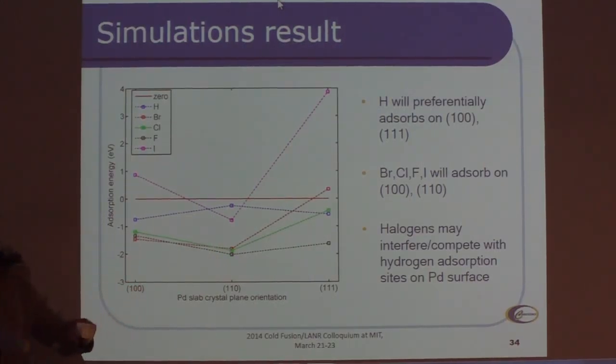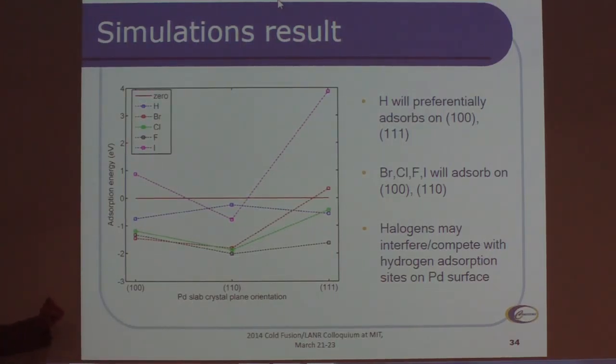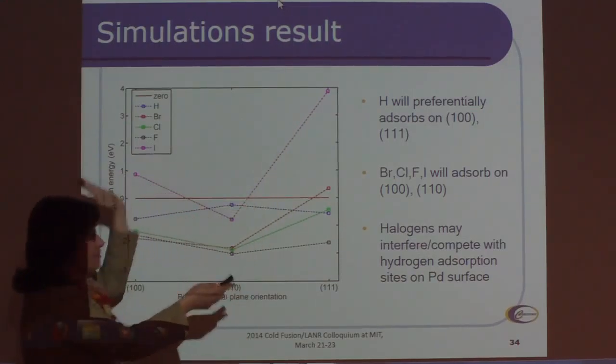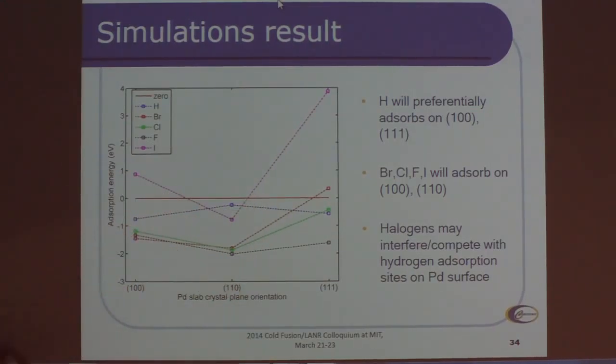Yes, that's why it's been blocking the etch, because that's where it wants to be. If we're aiming for a really anisotropic etch, actually our choice will be iodine. See how non-symmetrical this thing is? So that may really produce interesting features.